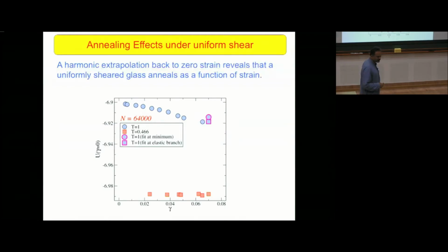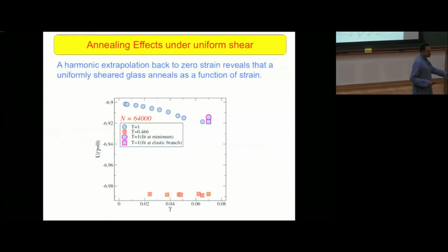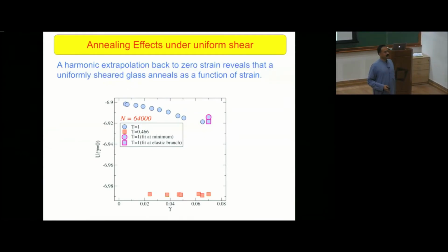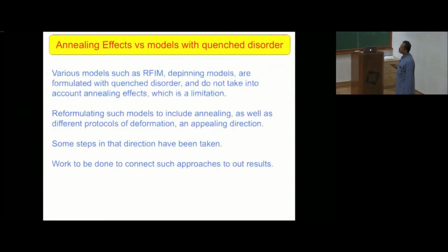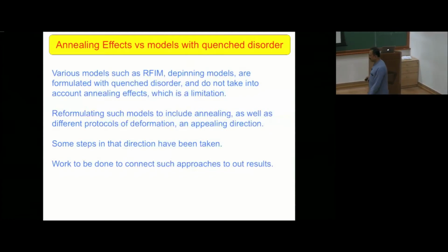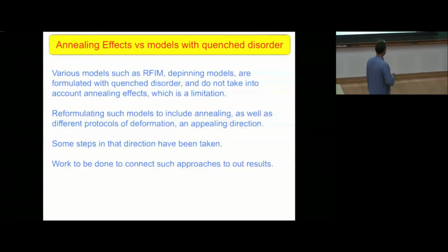These systems under uniform shear clearly anneal, right? Less obvious for the low energy, well annealed case, but this is what's relevant for these analogies with the random field Ising model critical point scenario, where even though the authors may not say it explicitly, you assume that disorder is quenched and fixed, and that's not really true. Okay. Like I said, there is some work that we can take advantage of, but we're in the process of trying to figure out how to put annealing into the picture and what we can say because of the detailed information that we have through these atomistic simulations about the nature of yielding.